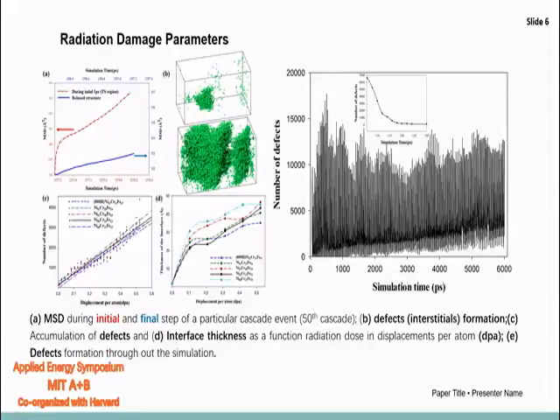We have plotted the thickness of the interface as a function of the radiation dose, and you can see that as the radiation dose increases, the thickness of the interface also increases. In the other figure, we have shown the defect formation throughout the simulation, and in the inset of that figure, we have shown the recombination process in a particular cascade simulation. You can see the defects get lower as the recombination process goes on.